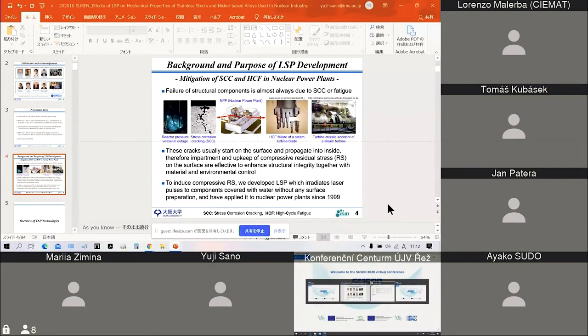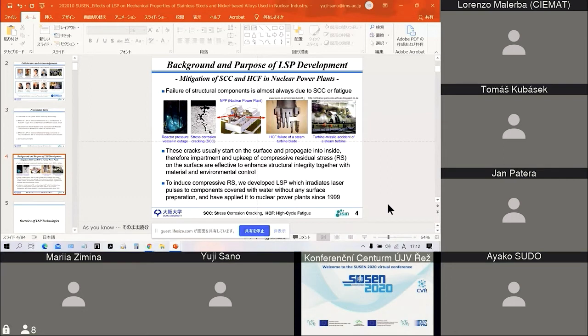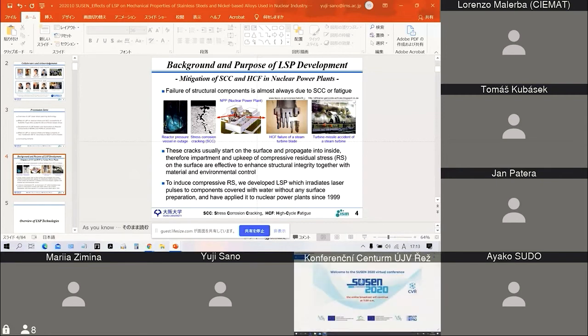As you know, the failures of structural components are almost always due to stress corrosion cracking or fatigue. These cracks usually start on the surface and propagate inside. Therefore, impartment and upkeep of compressive residual stress on the surface are effective to enhance structural integrity together with material and environmental control. To induce compressive residual stresses, we developed LSP, in which laser pulses are irradiated to components covered with water without any surface preparation, and have applied it to nuclear power plants since 1999.